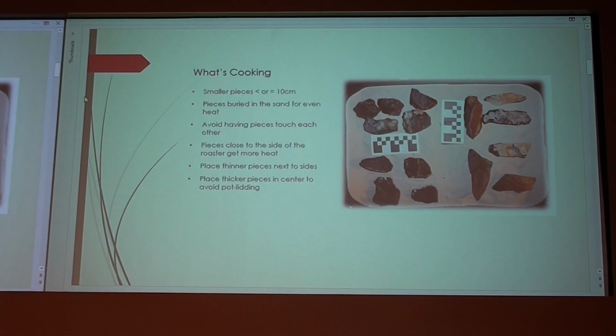So what's cooking? What I targeted was smaller pieces, less than 10 centimeters long. The reason for that is Knife River Flint, if it's fairly large, larger than that, is fairly easy to work. The idea here is that the smaller pieces, if you heat treat them, are easier to work. They pressure flake a lot better, and they percussion flake better.